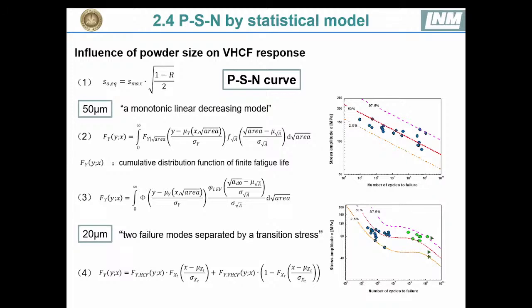And here, I assume that there is a monotonic linear decreasing model for this fatigue analysis, and then this PSN curve will be analyzed, and the SN curve for different failure probabilities is shown here. Also, if we consider two failure modes separated by a transition stress, then a stepwise SN curve is shown in this figure. And then we can also identify the different failure probabilities from these SN curves.